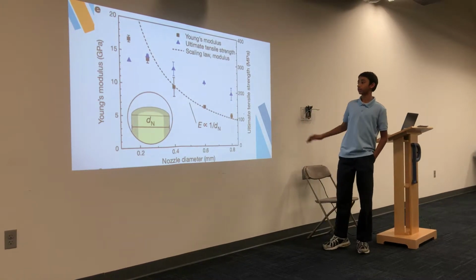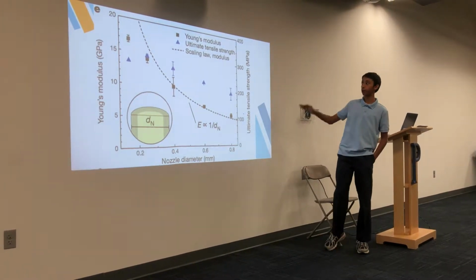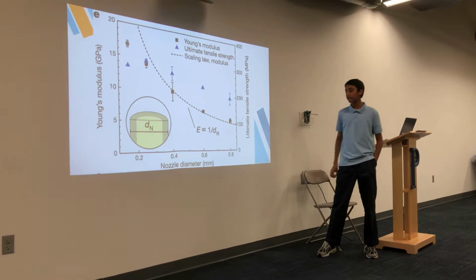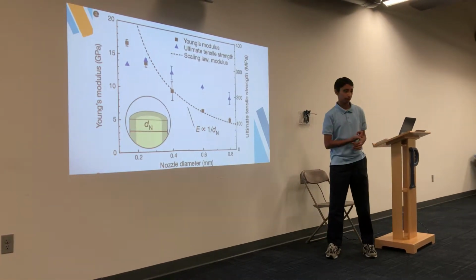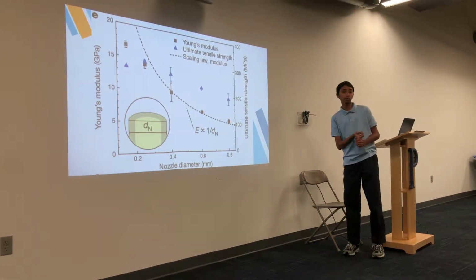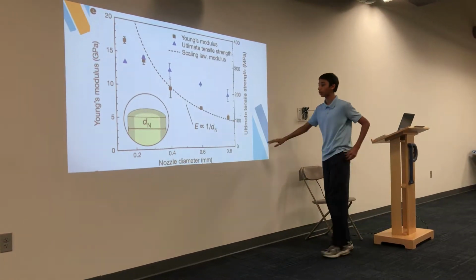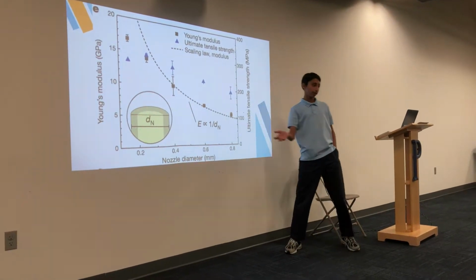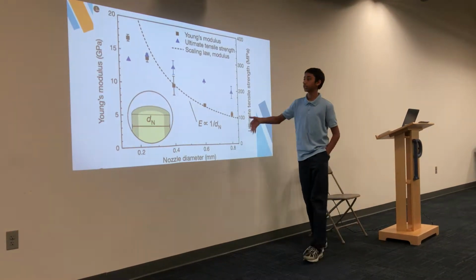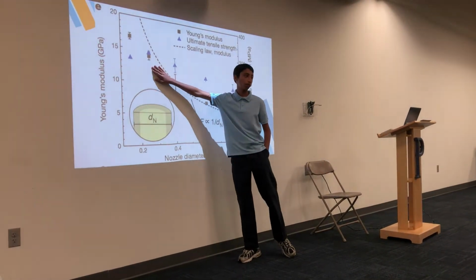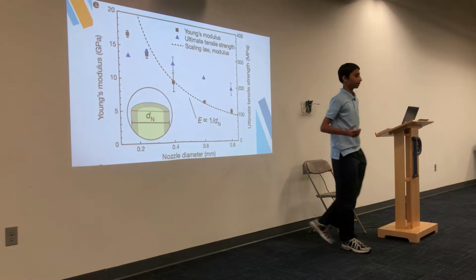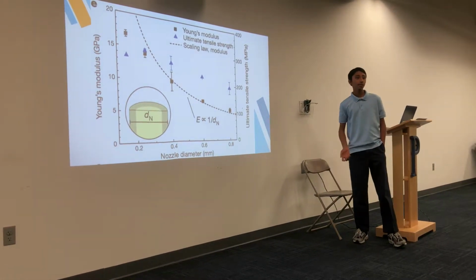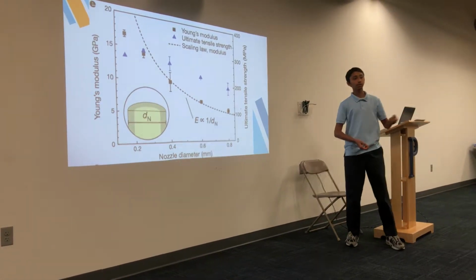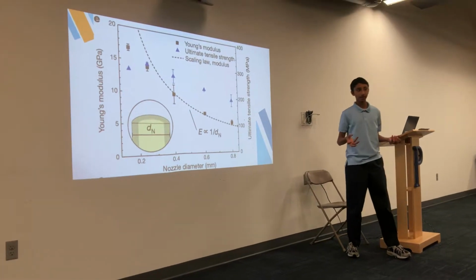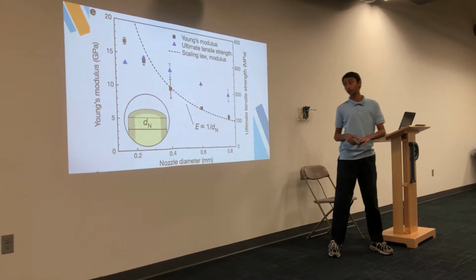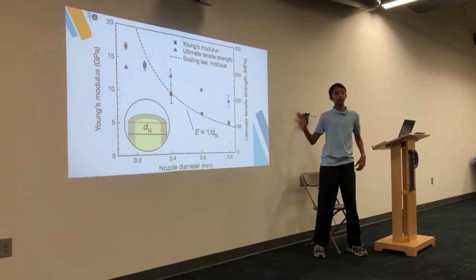So what you can see here, if you look at the curve formed by these two sets of points, is that the maximum Young's modulus, so the maximum stiffness and the maximum strength of the material, is going to occur when the diameter of the filament coming out of the nozzle, the extruder, is somewhere around 0.2 to 0.3. And this may seem like it doesn't make a lot of sense, because if you were to print something really thin versus something really thick, you would expect the thicker one to be stronger. But that's not how they did the test.